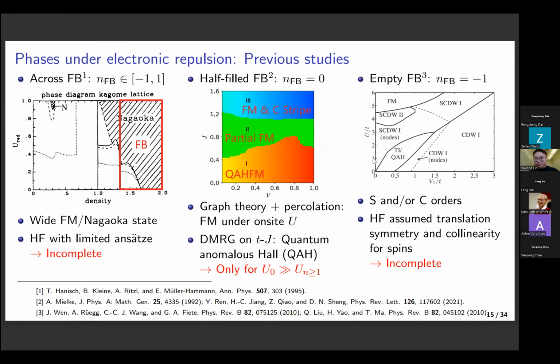Thirdly, people have paid a lot of attention to the empty flatband, that is N_FB equals -1, back around 2010. For example, some of the Hartree-Fock analyses have mapped out a phase diagram with a lot of spin and charge orders. However, in their Hartree-Fock analysis, they have assumed translation symmetry between the unit cells and spin collinearity in their phase diagram. So they cannot see states like 120-degree antiferromagnetic order or the tetrahedral order. So the phase diagram is also not complete in this sense.